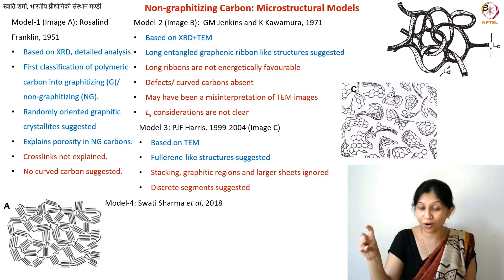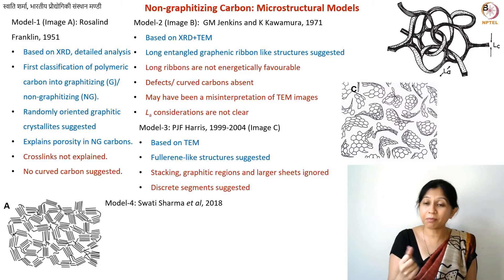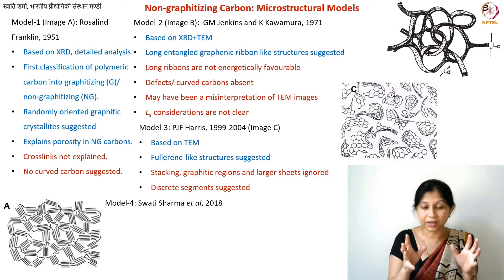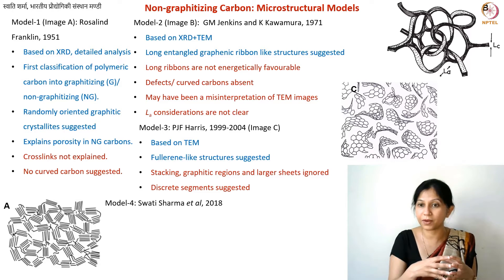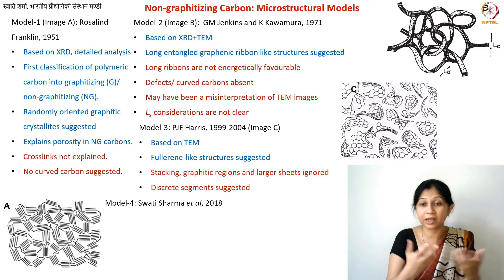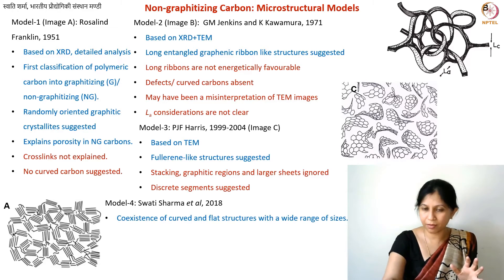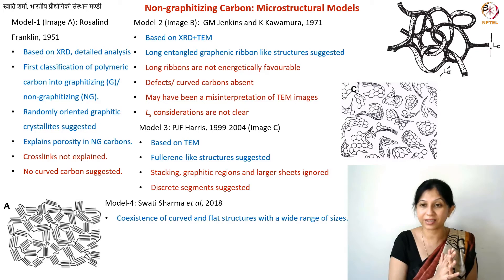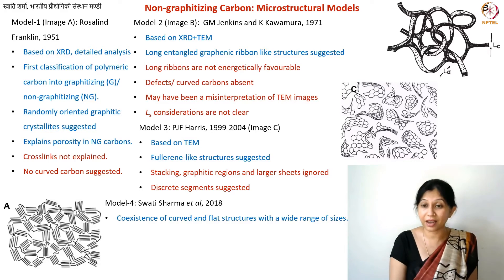Based on in-situ investigation of the entire carbonization process, we proposed a model. One limitation of our model is that it is so complex it is difficult to represent pictorially — if I make the image I'm proposing, it again looks as complex as a TEM image. What we found very interesting was that not just fullerene-like structures, but we also observed complete fullerenes in these carbons — some completely spherical-looking molecules.